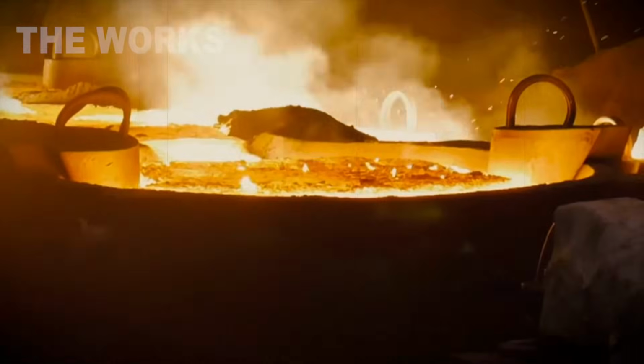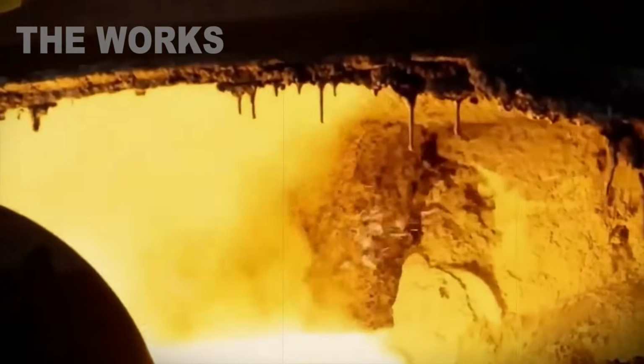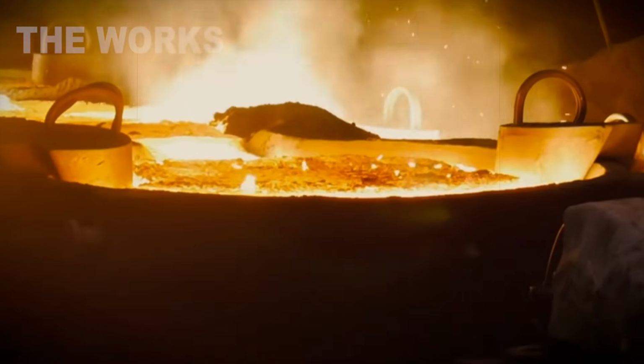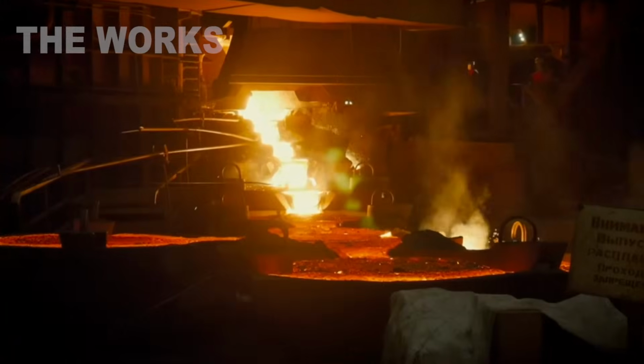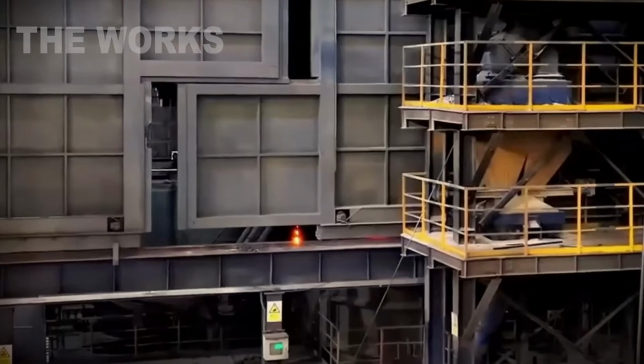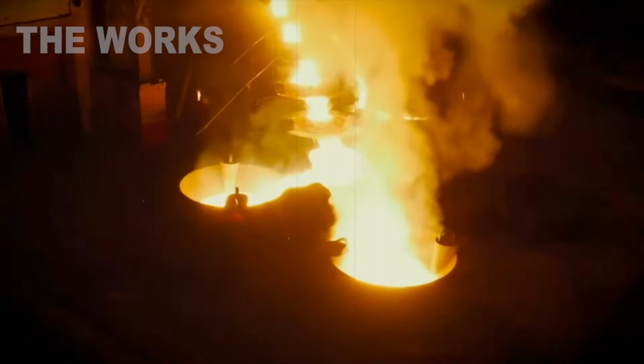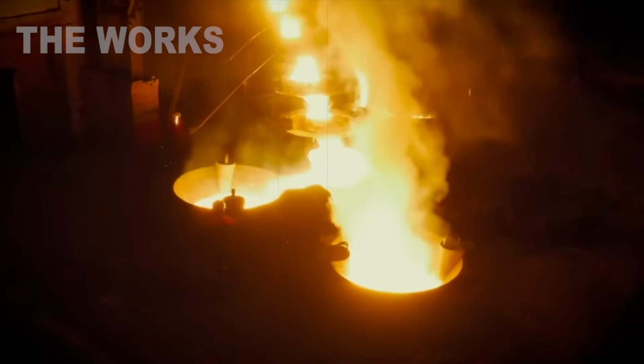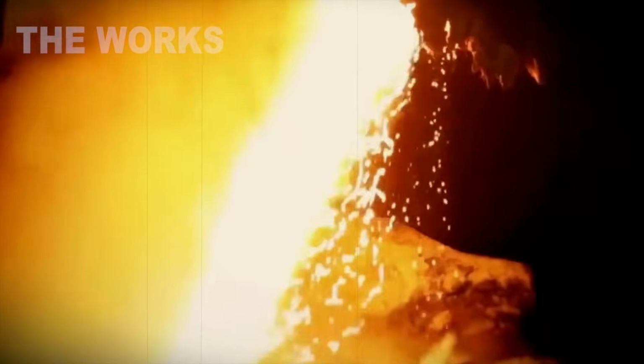This is bearing steel. Grade designation SAE 52100. Chromium content 1.5%. Chromium provides hardness and wear resistance. They pour the steel into a ladle. From the ladle into molds. Out come ingots, blanks weighing 5 tons each. Ingot dimensions 3 feet by 3 feet by 6 feet.